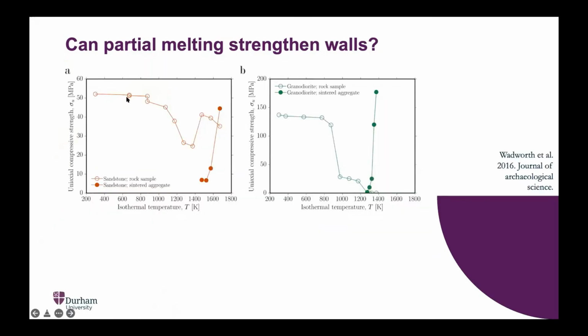What we found was that in both the sandstone and the granodiorite, so on the left is the sandstone experiments and on the right is the granodiorite experiments, we found that the intact rock got weaker with exposure to high temperature in general. And in the case of the sandstone, it got a bit stronger again before getting weaker at even higher temperatures. And in the case of the powder or aggregate of rock material, that had no appreciable strength up until a certain point, and then it got very, very strong very quickly.